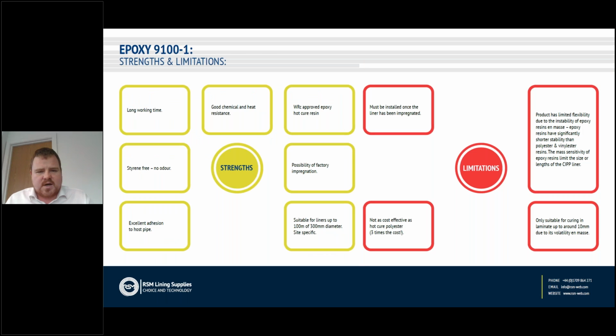Again, if we can just take a moment to look at the strengths and limitations. As I've already explained, it was the first WRC approved hot cure epoxy resin, giving the contractor or the engineer the peace of mind that this has been through not only ISO independent accreditation and ISO independent quality control, but also a third-party quality accreditation, excellent heat resistance, great working time, and also fantastic adhesion to the host pipe.